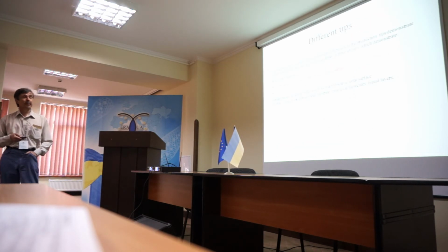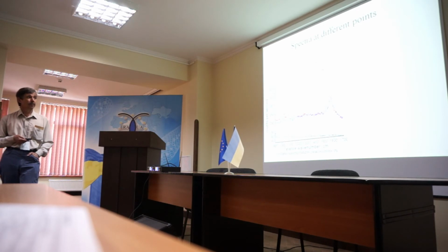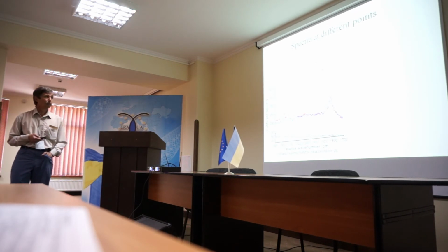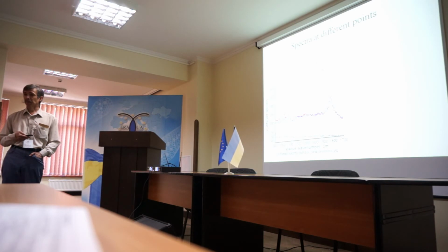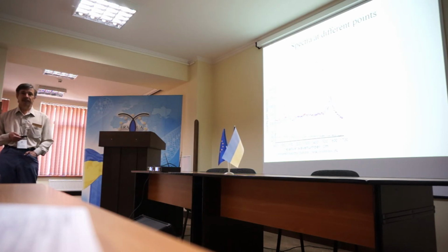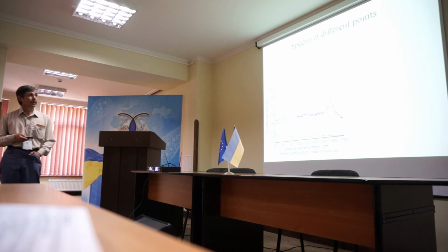So surely we have different tips, and we chose a tip with not so strong own enhancement to underline the influence of the gap mode, just the interaction with the surface. And in this case, we were not able to scan our surface, but you may see when we measure spectra at different points of a freshly prepared template-stripped gold layer, so rather clean in the first minutes, first hours, and rather flat substrate, you may see different shape of these spectra, different inclination, existence of some details in one spectrum, the absence in another.